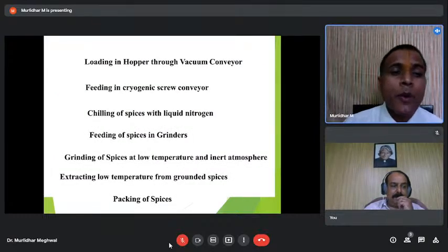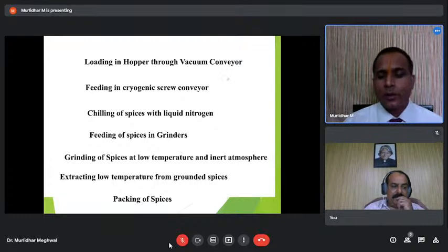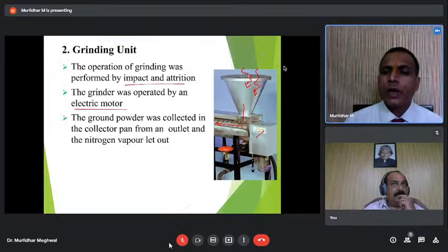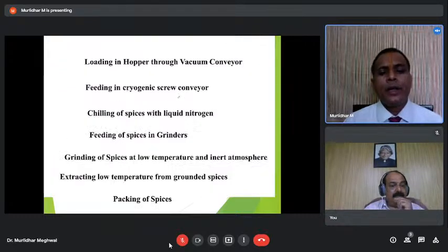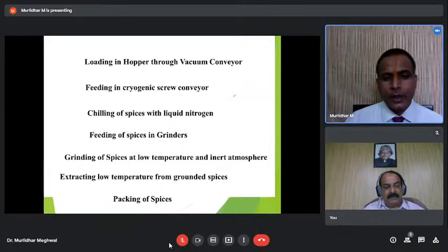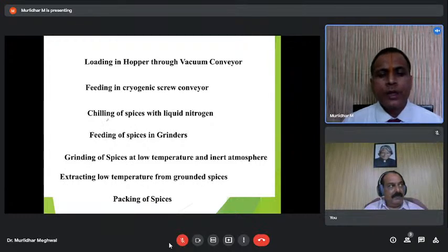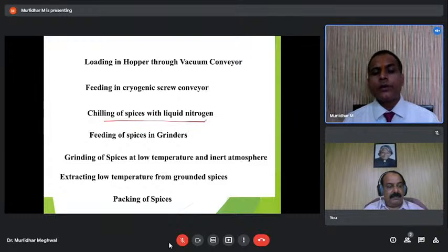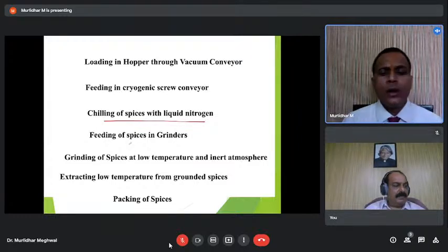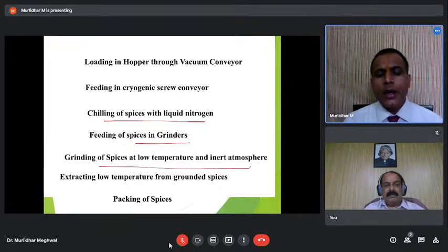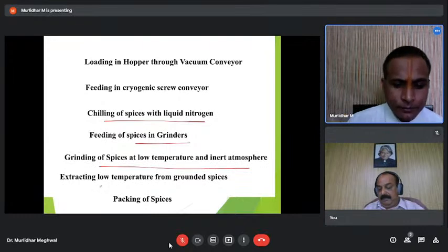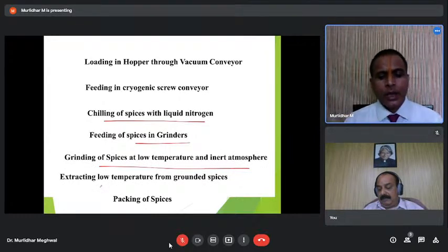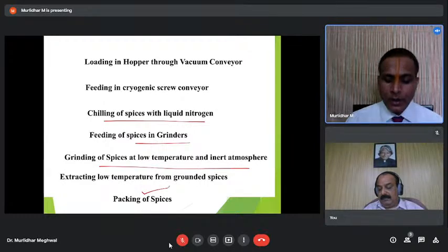So this is a flow chart. First we will be loading the hopper through the vacuum container conveyor. So this kind of hopper structure we have. Then we have feeding in the cryogenic screw conveyor. From the hopper it will be taken to the screw conveyor. Then chilling our spice with liquid nitrogen. From the other side we apply the liquid nitrogen so that we do chilling. Then feeding our spice into the grinders, and then grinding our spices is done at low temperature and in an inert atmosphere, and then we bring it to room temperature, and finally we do the packaging of the spices.